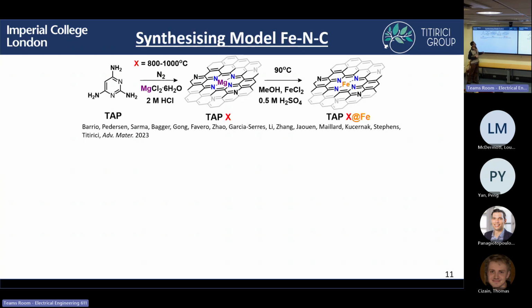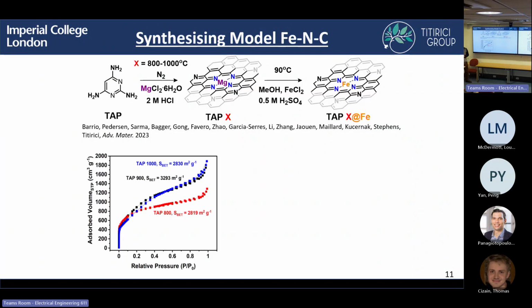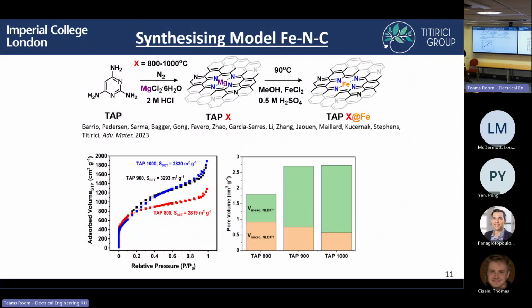And then we load our iron at low temperature, as I mentioned before. So we did this with a methanol reflux method at 90 degrees with iron chloride, and then afterwards we wash the material in acid. And the very interesting thing about this material is we end up with incredibly high surface areas and porosity. So we end up with over 3,000 meters squared per gram from the BET analysis, especially for TAP 900. And we see that as we increase the pyrolysis temperature, we see an increasing amount of mesoporosity and decreasing amount of microporosity. And normally these types of catalysts, they're say just dominant in microporosity or just mesoporosity, but here we have quite a suitable amount of a mixture of the two.